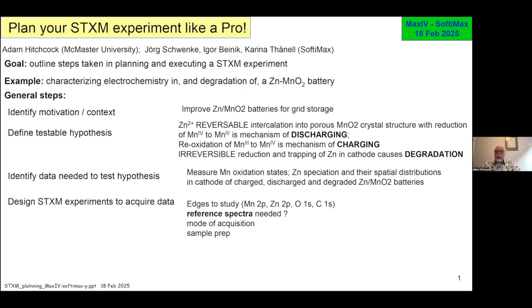We know STXM is able to cover a number of different elements in the soft X-ray regime. The soft X-ray regime is actually extremely good for characterizing the immediate environment of elements because the intrinsic resolution in terms of lifetime is very good, and it is well matched by the properties of the beamlines that are used for STXM, and the sensitivity to different chemical states is actually much better in most cases as compared to, say, the K-shell edges of the 3D transition metals, which are not sensing the d electrons, which are where the active oxidation state changes are happening.